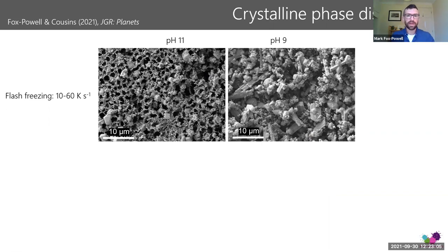by using our sublimation technique, we are able to remove all the ice from these crystallized brine veins and actually look at the salt partitioning, the crystal phase partitioning that's going on within the brine vein. So now we're down on a scale which is in the sub-brine vein scale. And you're seeing here both pH 11 and pH 9